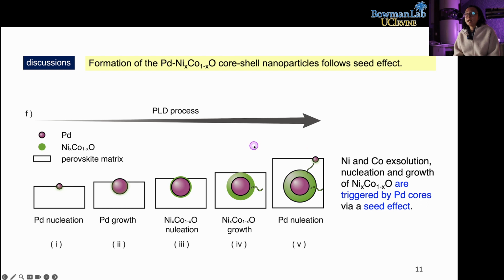Palladium exsolution and growth trigger the exsolution of nickel and cobalt to form the shell in the surroundings, making the core-shell structure. So the nickel cobalt exsolution and nucleation growth of the nickel cobalt oxide shell are triggered by the palladium core via a seed effect. The palladium will nucleate and grow, and in this process, the palladium will trigger exsolution of the nickel cobalt, which grows like a shell structure in the surroundings.